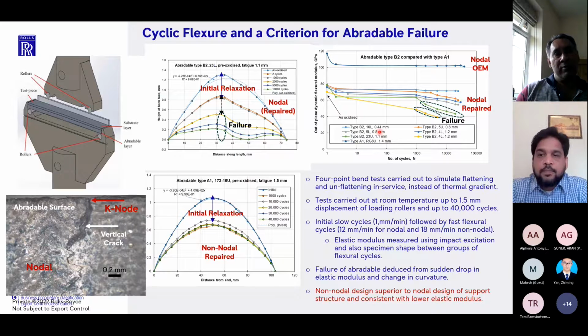So rather than doing a thermomechanical test at high temperatures, we tried to do the same thing but at room temperature. Rather than depending on a temperature gradient, we actually applied a load. So the flattening and unflattening at room temperature was produced by a 4-point bend test approach. We produced the same effect, but by applying a load, in a way to try to understand the failure responses of a nodal versus a non-nodal design.